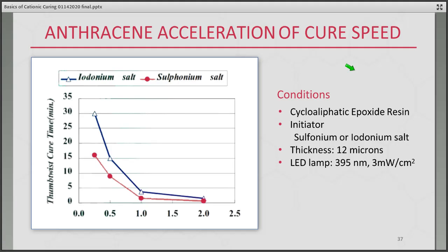Here's some work that was done comparing iodonium salts and sulfonium salts, to illustrate how well they can accelerate your cure speed in a cationic cured coating. Blue is iodonium, the red is sulfonium. At a straight base formulation, this is a thumb twist cure, so basically putting your thumb on your cured coating and seeing if you make an impression. So perhaps 15 minutes for the sulfonium under lab conditions, 30 minutes under this experimental condition for iodonium.